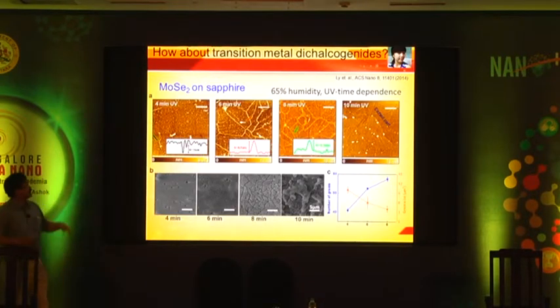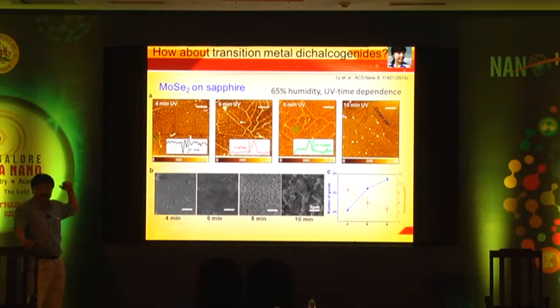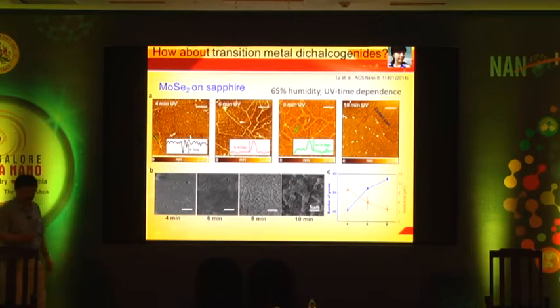Anyway, the same idea can also be applied for any kind of TMD materials. In this case, molybdenum diselenide on sapphire. We can simply again oxidize a sample and observe this kind of grain boundary. So the idea works for any kind of material.